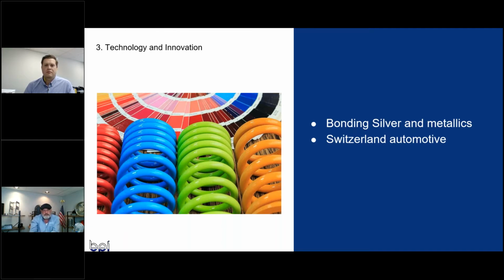But if you have a heavily post-blended metallic, you have to spray to waste, because if you try to reclaim it, you get it out of balance, and then the color just goes dramatically sideways.